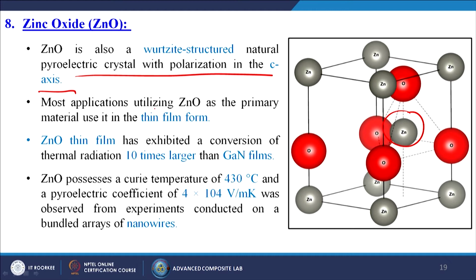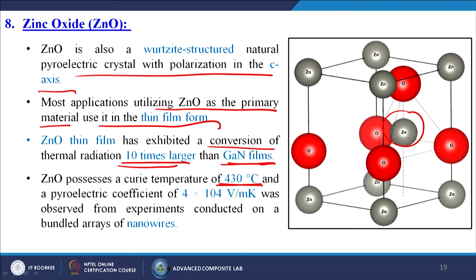Most applications utilizing zinc oxide as the primary material use it in the thin film form. Zinc oxide thin film has exhibited a conversion of thermal radiation 10 times larger than the gallium nitride films. Zinc oxide possesses a Curie temperature of 430 degrees centigrade, and a pyroelectric coefficient of 4 x 10^4 volt per meter Kelvin was observed from experiments conducted on bundled arrays of nanowires. So, people have done lots of work on zinc oxide and it is a wonderful material for generating